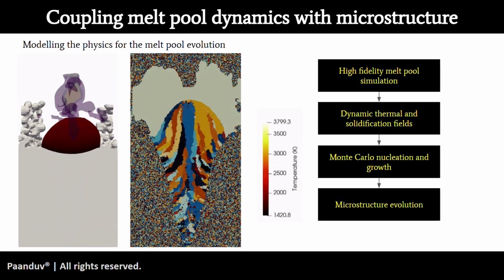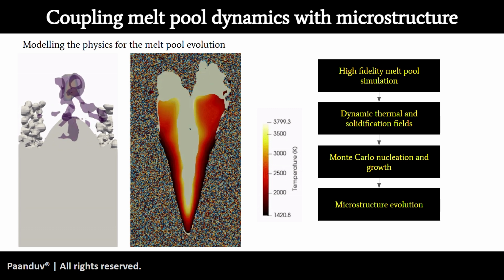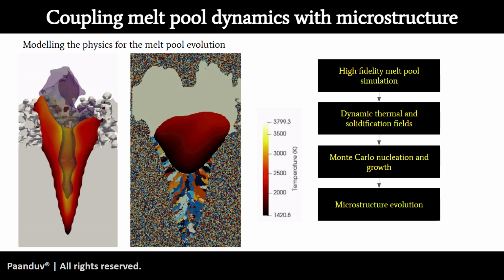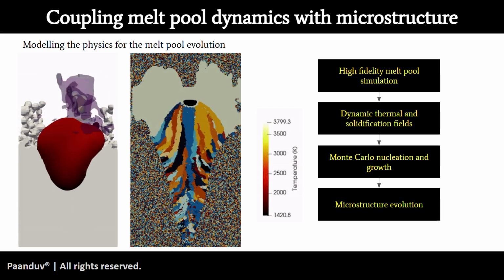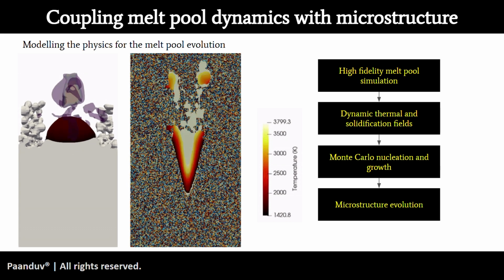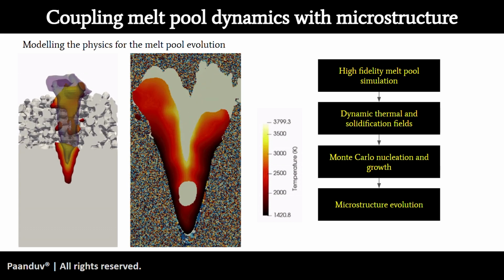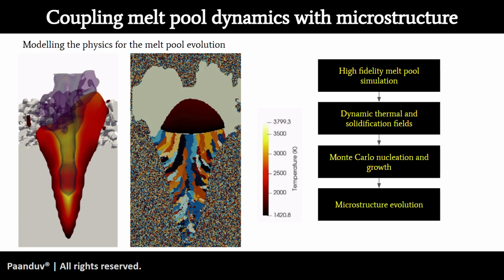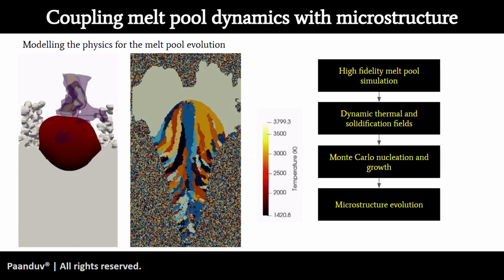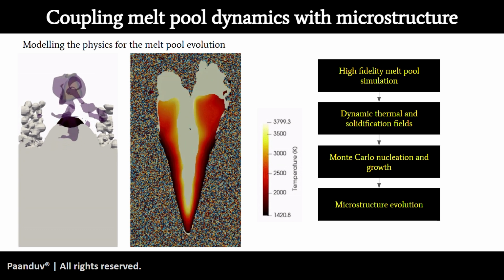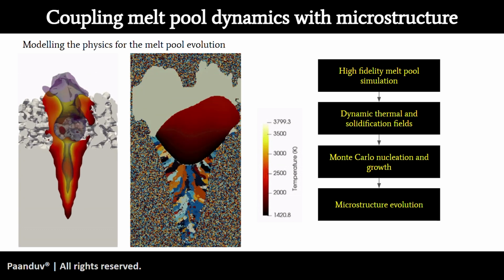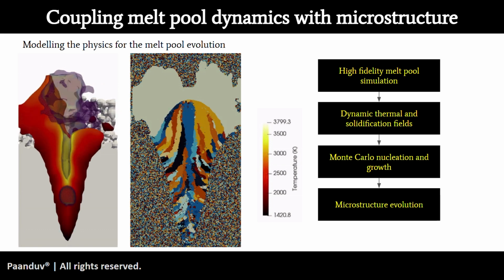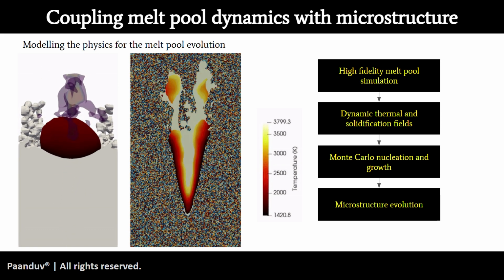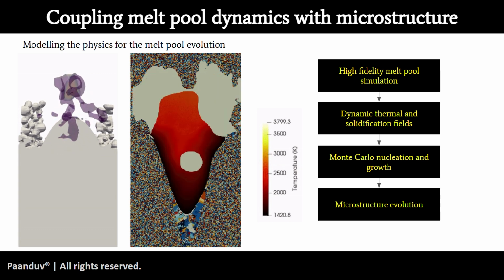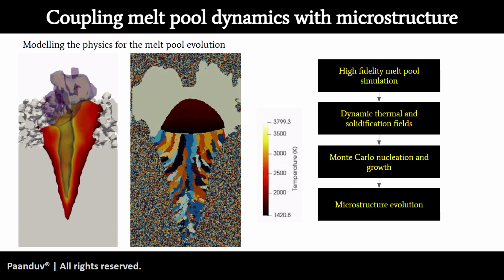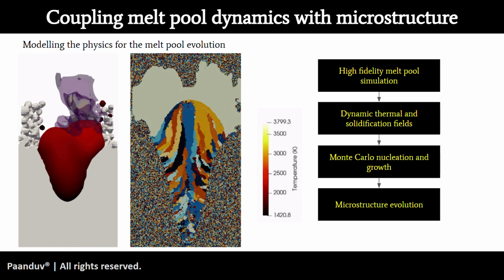Now, it is very important to couple the melt pool dynamics, which is happening at a continuum scale, where your momentum conservation, your energy conservation, your mass conservation, your phase change, solidification, everything is happening. It is very important to couple that entire gamut of computational fluid dynamics with microstructure data. To that effect, what we are seeing on the screen on the left hand side is the evolution of a melt pool. You can even see how nicely the vapors are trapped at the hump on top of this bead. And when the same results are projected and solved using the microstructure algorithms available inside AM PravaH, you can see how the grains have evolved over time.